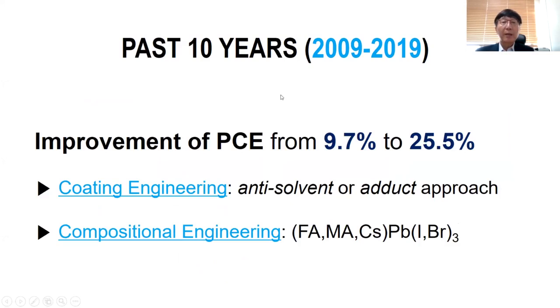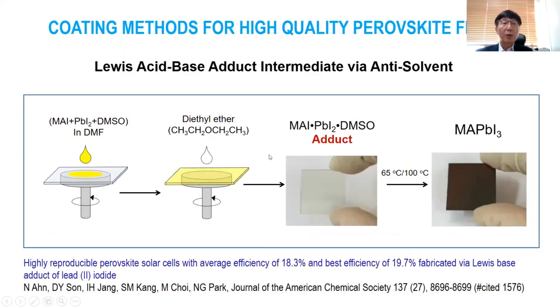And over the past 10 years, the efficiency was significantly improved from 9.7% to 25.5%, which is pretty close to crystalline silicon solar cell. They're almost comparable. And this efficiency improvement was realized by coating engineering and compositional engineering. For the coating method,